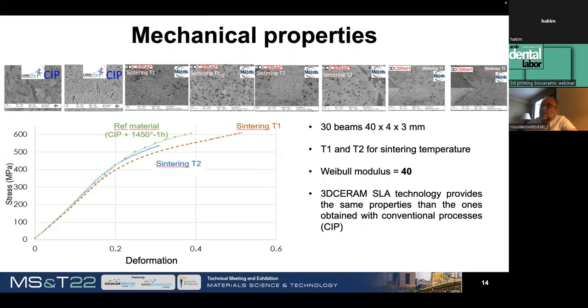And that's why I explained to you that the company started with the ceramic engineers, and our roots, our genesis is ceramics. So having this ceramic knowledge, this ceramic expertise, these resources in-house helped a lot to develop these post-process steps, which is sintering mainly. Because sintering regime, sintering temperature, soaking time change a lot the property of the material itself. As you can see on the diagram, you see 3 lines. The green one is our reference material, which is called isostatic pressed zirconia. And this is a reference for us to follow, because at least the printed material has to be equivalent to this reference conventionally manufactured material.